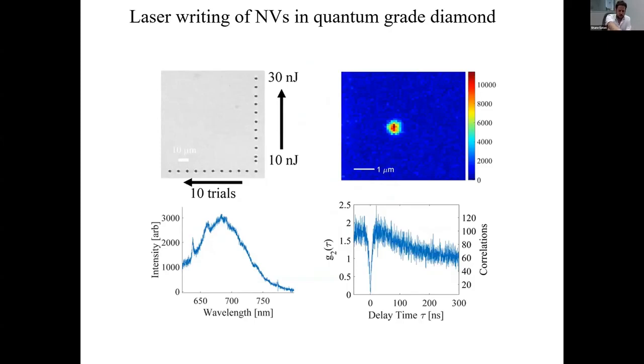Here on the top left, we show an overhead microscope picture of an array of the static exposures we formed. Now, these visible dots were essentially marker dots, so we could find this sort of invisible array because you can't see them by eye, you can't see them by microscope. So they were written with quite high laser pulse energies. But essentially what we found in this low pulse energy range, we could achieve single NV centers, again, with 50% success rate.